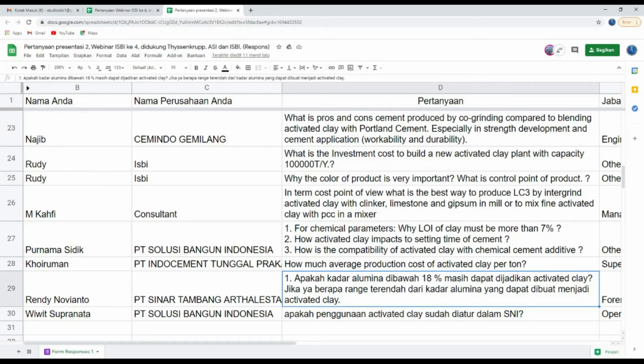And then what is the lowest range of the alumina content that is used for the activated clay? Yeah, the typical range is something around 16, 17, 18. So most of our samples fulfill these criteria. But as I said, we can have a detailed look at this material. If you say this is my preferred quarry, you can just have a rough view on the chemistry as well as on the mineral composition. It's not that expensive, and then it gives you an indication. If this is important for you, to maybe use another type of clay, we should have a look at it before saying whether it is possible or not possible to be used.